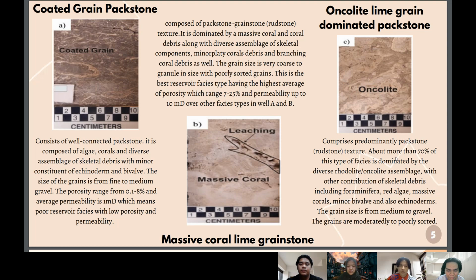The first one is coated grain packstone. This facies 1 consists of well-connected packstone, composed of algae, corals, and a diverse assemblage of skeletal debris with a minor constituent of echinoderms and bivalves. The size of the grains is from fine to medium gravel, and the porosity ranges from 0.1 to 8%, and the average permeability is 1 md, which means that this facies 1 is a poor reservoir facies with low porosity and permeability.